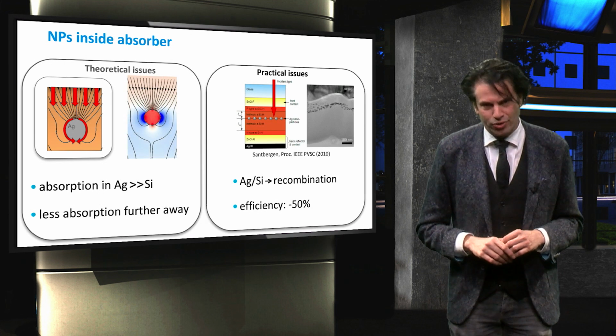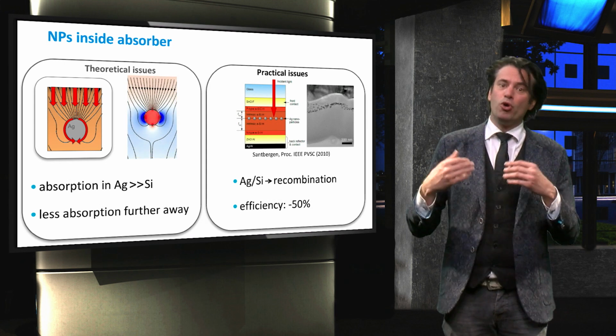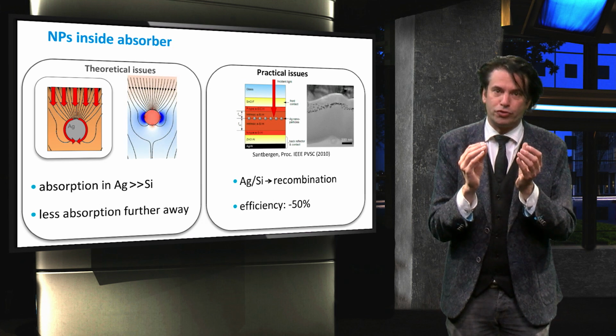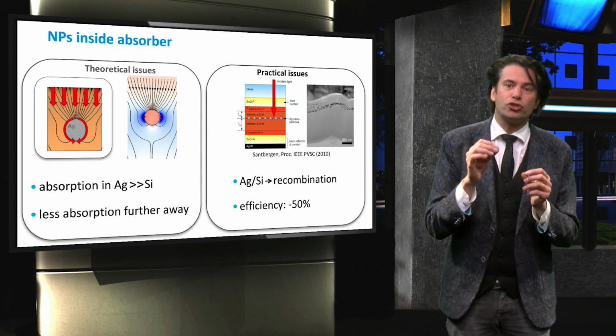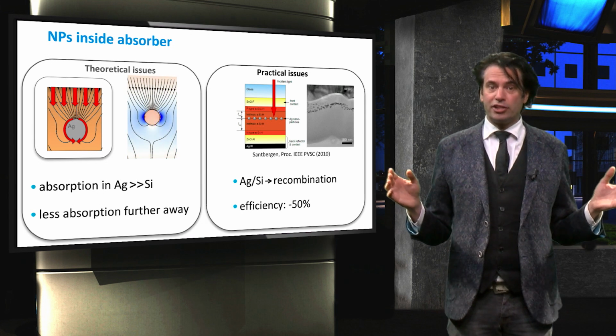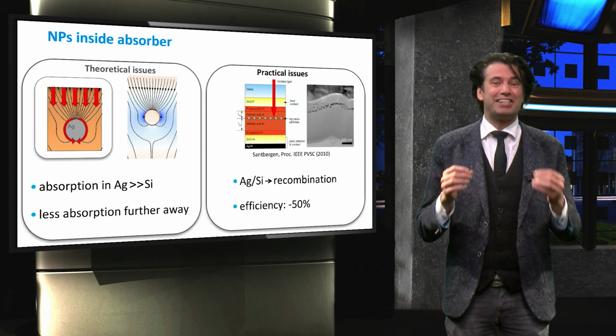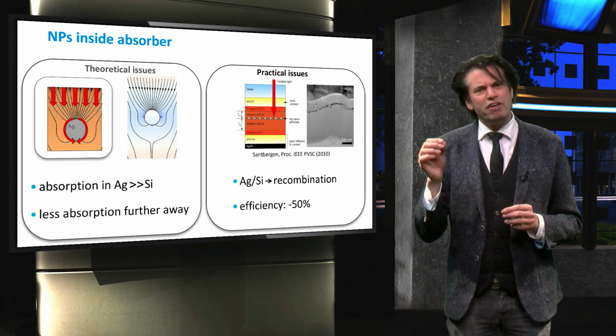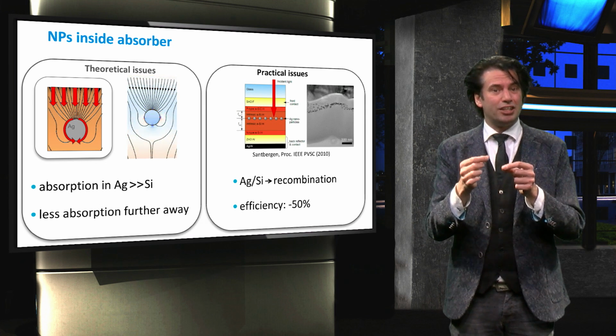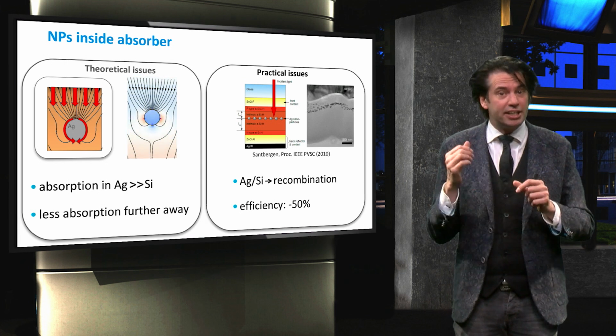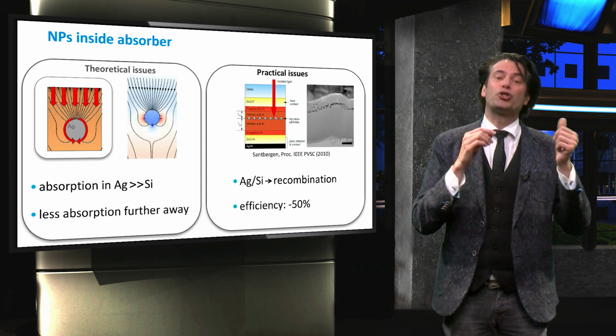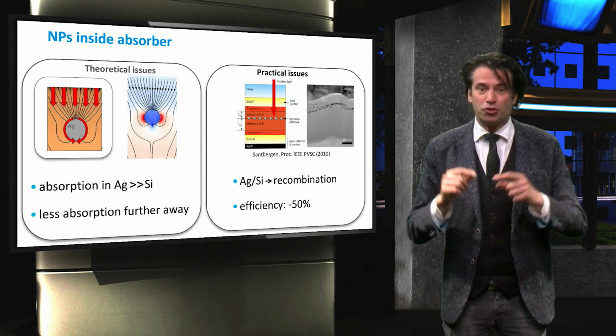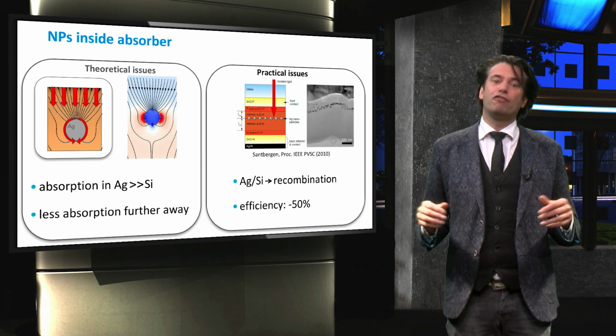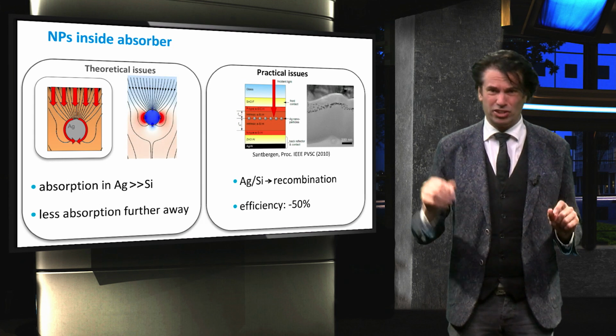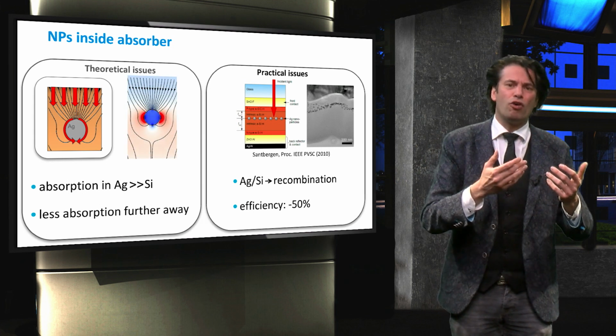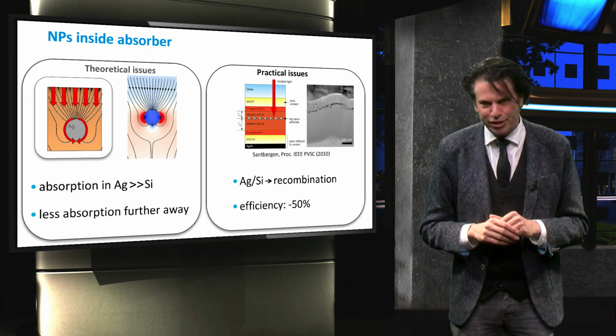Then there are also some practical issues. The absorption is enhanced mostly within a few nanometers from the metal surface, which implies that the metal and semiconductor should be in contact. However, this creates a silver-silicon interface at which photo-generated charge carriers can recombine. When we fabricated thin-film silicon solar cells with silver nanoparticles embedded inside the absorber layer here at the Delft University of Technology, we found that the current, voltage and fill factor all dropped significantly. As a result, the efficiency of all devices was reduced by at least 50%. This demonstrates that this approach requires passivation of the metal surface, which in my opinion will be very challenging and complicated.